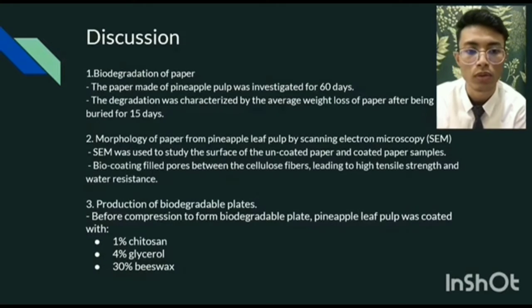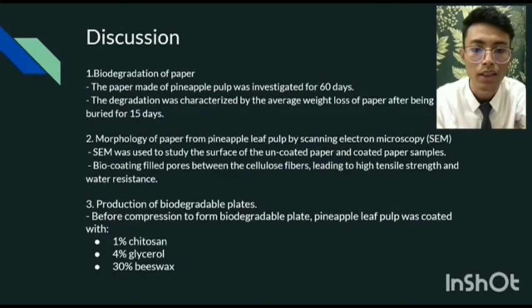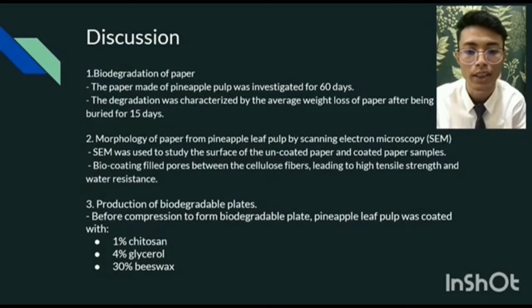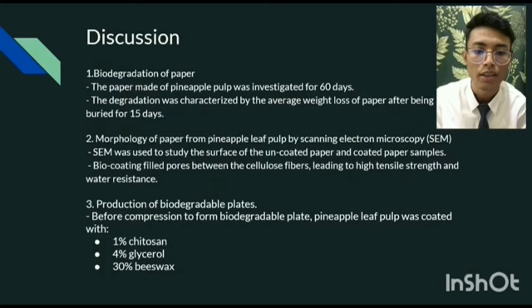First, I want to talk about the discussion in this study. It tells how the degradation of the paper plate made from pineapple pulp was studied. The paper plate was investigated for 60 days, and the degradation of the paper plate was characterized by the average weight loss of the plate after being buried for every 15 days.